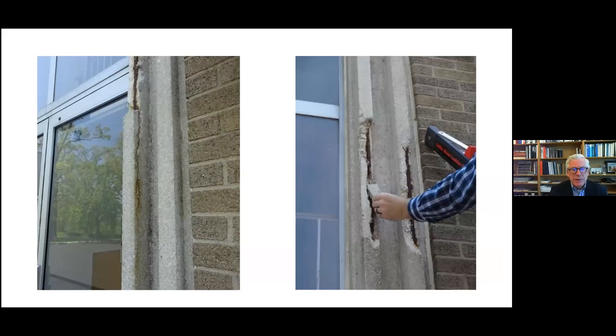So the investigation focused on the architectural precast concrete. That's what we'll cover in this presentation. The concrete itself was defined by a white cement matrix with exposed quartz aggregate in some architectural curved projecting ribs. The distress conditions include cracking and corrosion of embedded reinforcing steel. Most of this had to do with a thin profile of concrete cover, which were the areas of the most significant repair work that was needed. Laboratory testing and petrographic analysis was performed. And once again, carbonation levels had reached the level of the reinforcing steel, which was the primary driver of the deterioration.